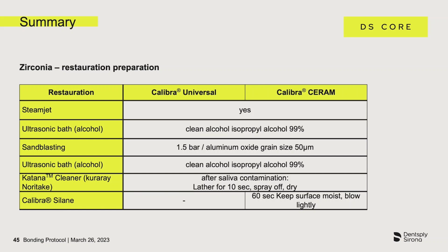It is important that all salivary proteins are removed from the surface of the restoration prior to adhesive cementation so that the adhesive bond can take place without interference. The chemical bond between zirconia and composite cement is achieved by MDP.